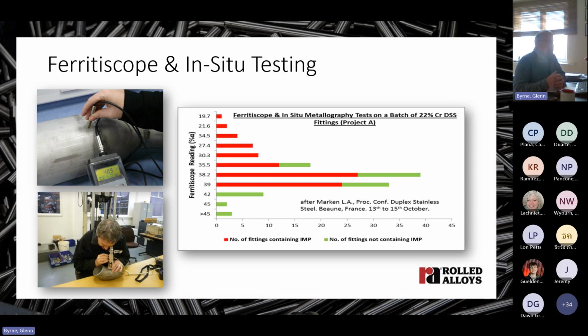Now, this check has the benefit of being non-destructive, so the batches that are found to be sensitized in the mill or in the warehouse can be recovered by reheat treatment. But this should only be done after a root cause analysis to identify and correct the errors in the heat treatment process that caused the problem in the first case.